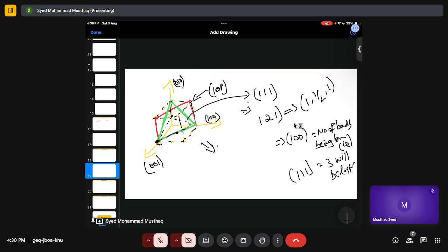So from here you know that if I'm talking about the surface energy of any crystal, all you have to do is find the number of broken bonds, n, times 2, which is coming from there, times the delta H melting of that system, whether it is copper, aluminum, whatever it is, divided by Avogadro number times the coordination number of atoms in that crystal structure. So this is my formula.